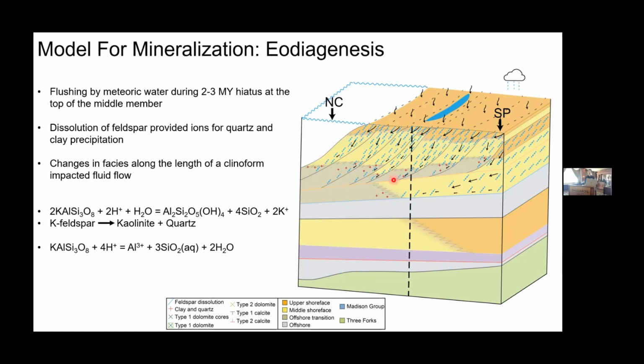So relating this back to what I talked about earlier, there's kind of two different pathways we could have taken here, depending on whether we were an open or closed system, and that probably has some relationship to facies, as fluid would have moved more easily through those higher energy, higher permeability sediments at the top versus those at the bottom. So it could have gone from potassium feldspar to kaolinite and quartz, or just went straight to an aqueous phase from potassium feldspar and then was transported away from the solution.